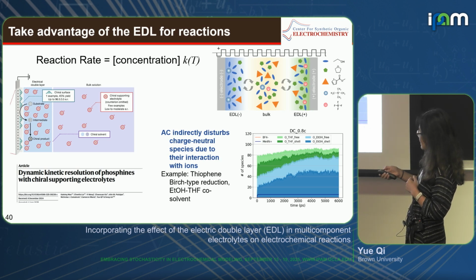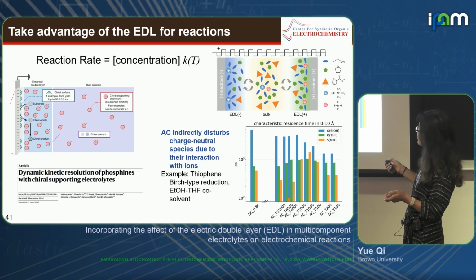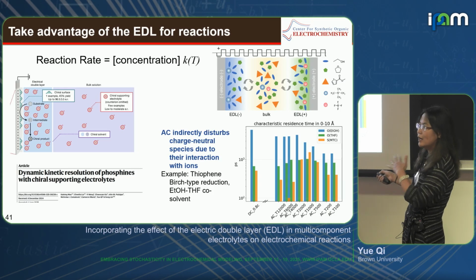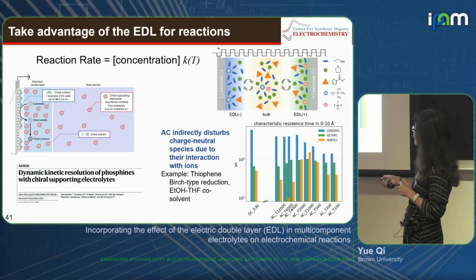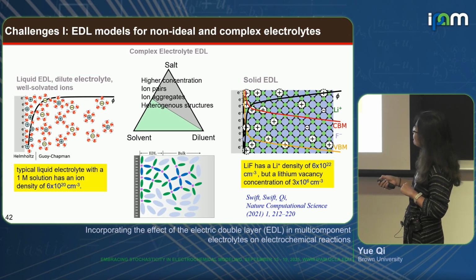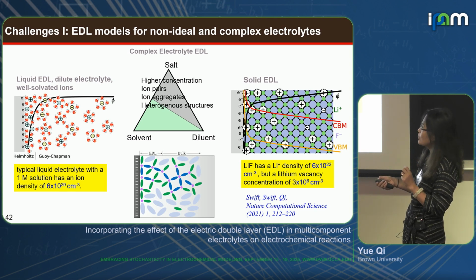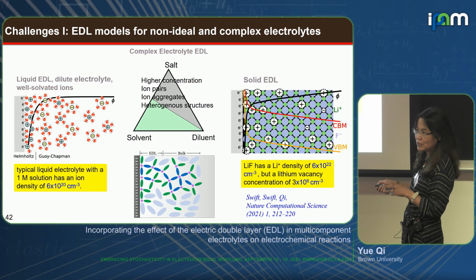And so when we change from DC to AC, we can dramatically reduce those ion-associated species near the interface. And so you can change the frequency to tune the surface concentrations and prevent the bad side reactions. Right? So I hope I convinced you that the double layer does not just consist of ions. There are many species in this double layer. The charge neutral species get redistributed as well.